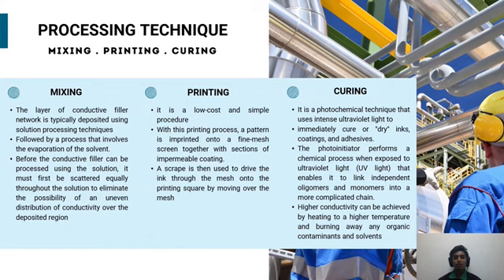Okay, first, mixing. The layer of conductive filler network is typically deposited using solution processing technique, followed by a process that involves the evaporation of the solvent. Before the conductive filler can be processed using the solution, it must first be scattered equally throughout the solution to eliminate the possibility of an uneven distribution of conductivity over the deposited region.